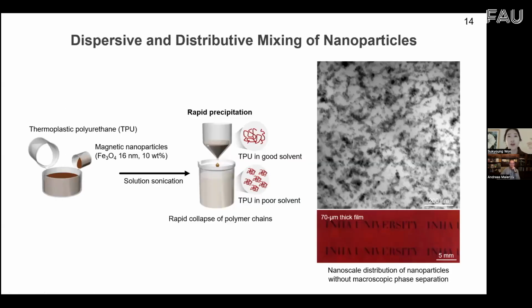So we implement the rapid precipitation method for achieving the distributive mixing of these magnetic nanoparticles. First, the polyurethane and the nanoparticles were mixed in a good solvent, which expands the polymer chains by increasing their radius of gyration. Then the polymer mixtures were rapidly precipitated in the poor solvent, which contracts the polymer chains by reducing their radius of gyration. This rapid polymer collapse trapped the nanoparticles, preventing macroscopic phase separation. And we can see this nanoscale dispersion of the nanoparticles in this thermoplastic polyurethane matrix.